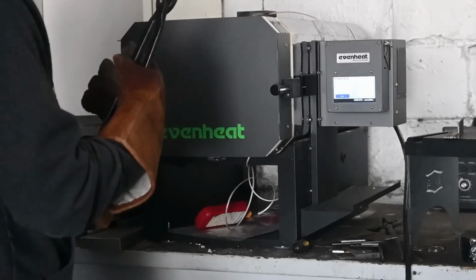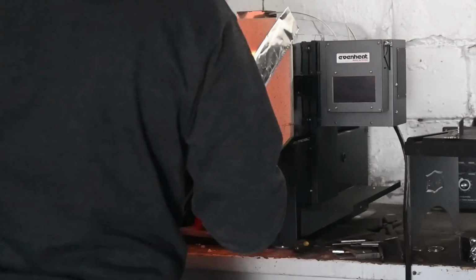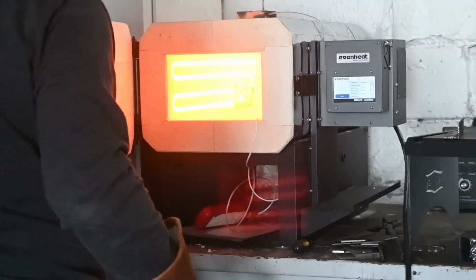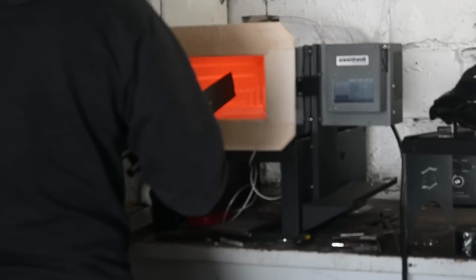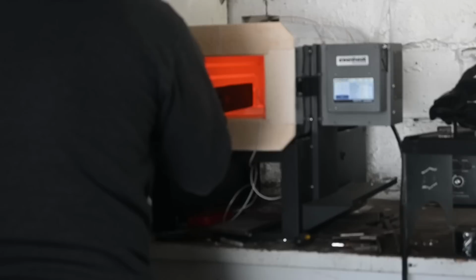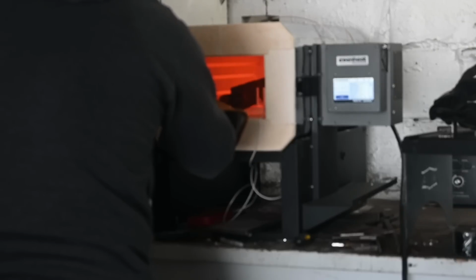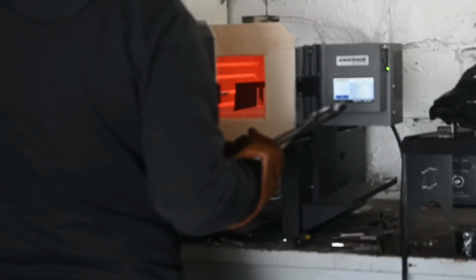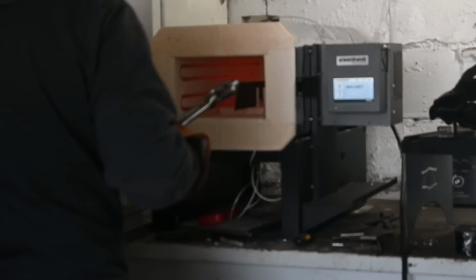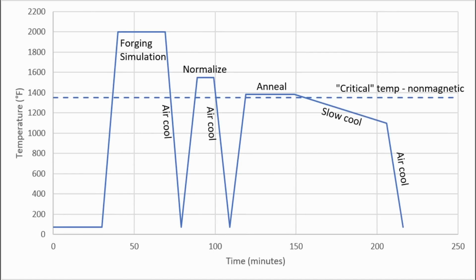So first I did a forging simulation at 2000 degrees Fahrenheit for 30 minutes, and I air-cooled. Then I normalized at 1550 for 10 minutes and air-cooled, and then I annealed by holding at 1385 Fahrenheit for 30 minutes, and then cooled at 300 degrees per hour down to 1100 degrees, and then I just let it cool in the furnace. The cooling rate below 1100 degrees doesn't really matter because the transformation has already happened. So in the annealed state, the steel was nice and soft, slightly harder than it came from the mill, but it also probably has a finer microstructure, which I think is probably a good thing.